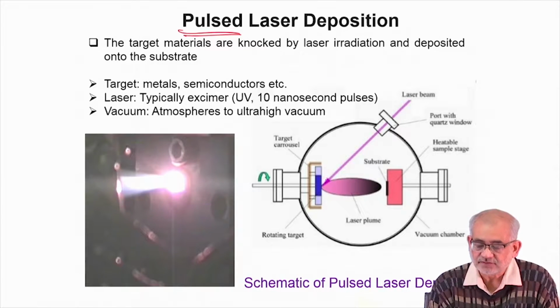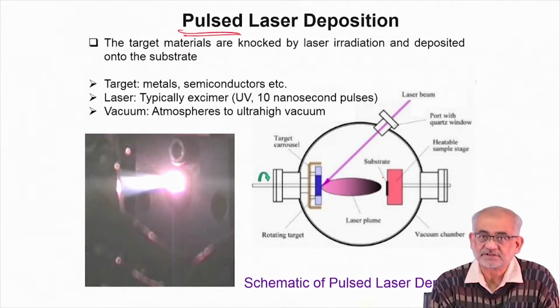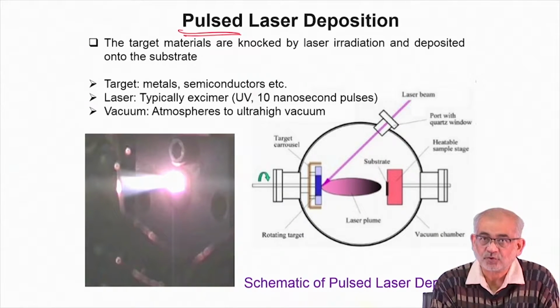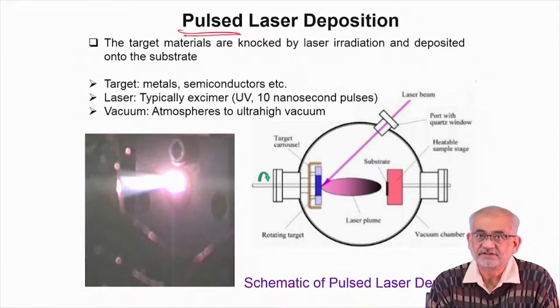Now this is how we can also create a clad layer, but the thickness of that clad layer will be fairly small. So here we may use this either for semiconductor applications, various device applications where we need a very thin layer, or even in metallurgical applications we can use this as a final layer which can close the pores and other defects on the surface and create a thin layer of a very different and a matching composition.